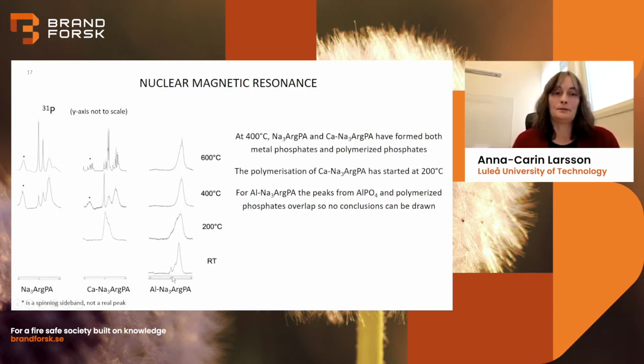Aluminium is a bit of a problem because the signal from aluminium phosphate is in the same region as we expect peaks from polymerized phosphate. So we cannot really say if the aluminium version of our flame retardant also polymerizes, or if it's just forming phosphate, or if it's a mixture, but probably it is a mixture.